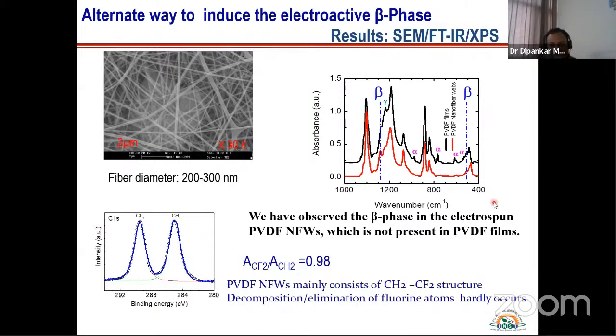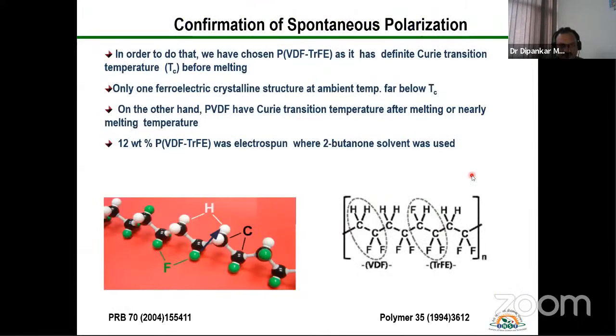So this is one experimental proof that the electrospinning technique is very good to induce the beta phase. You can see this red curve after electrospinning, this phase is coming out, meaning that we have the beta phase, which is not available in the case of simple solvent casting film. There is no peak here. So this is one of the good techniques to induce the piezoelectric phase.